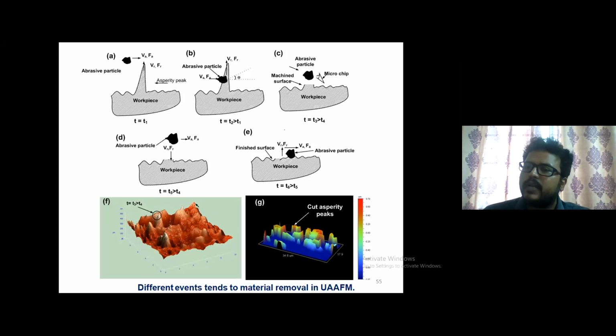So we will not remove the material like we remove the material in a milling machine or lathe machine. Here we remove the material in microns, in very small size, and that too with control. So here you can see the initial finishing of the material itself will take 1 micron, that is, the initial state before doing AFM. After finishing, you will go to nano level, 0.001 micrometers. So this is a super finishing process, and our material removal rate will be very low.